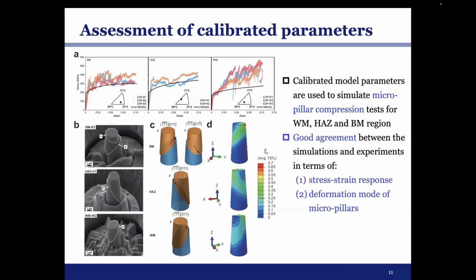However, such a way of calibration may raise one question, whether these parameters are good enough to describe an individual single crystal. So in order to confirm this parameter calibration, we do micropillar tests for different regions. So the three regions, that is base metal, weld metal, and heat affected zone. And we use the parameters that we calibrated with tensile test data to see whether these parameters are good enough. As we can see here, there's a good agreement between the simulation and the experiments in terms of the stress strain response, as well as the deformation mode of individual micropillars.